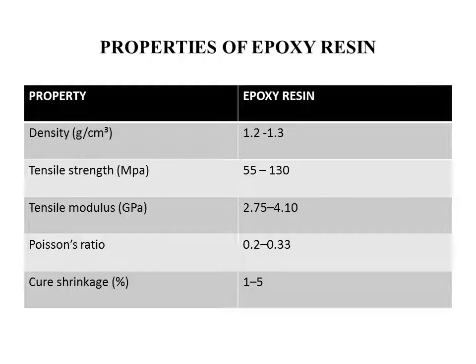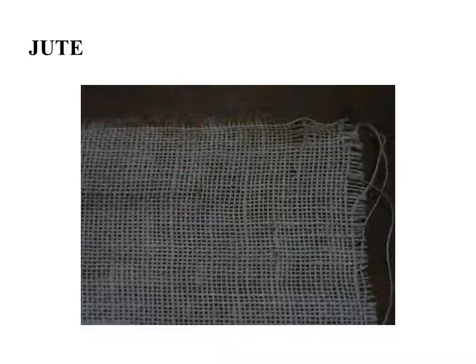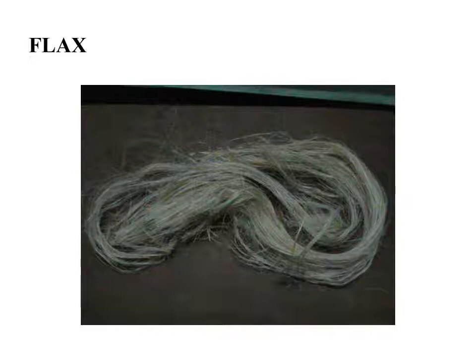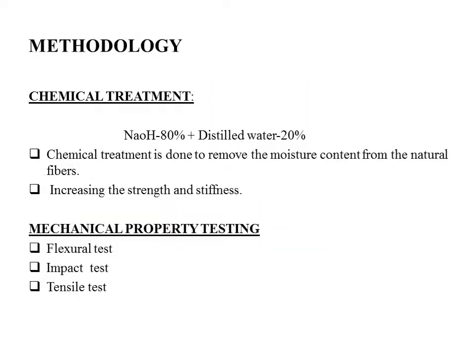And the properties of epoxy resin. Density is 1.2 to 1.3 grams per centimeter cube, tensile strength is 55 to 130 megapascal, and the tensile modulus is 2.75 to 4.10 gigapascal. Compared to all other epoxy resins, it has a very good tensile modulus. Poisson ratio is 0.2 to 0.33. Shrinkage percentage is 1 to 5. This is our matted jute fiber, and this is our continuous flax fiber.